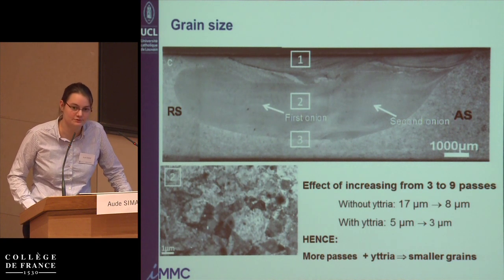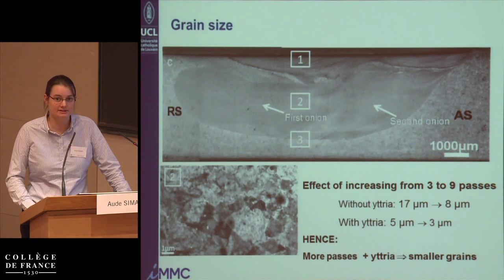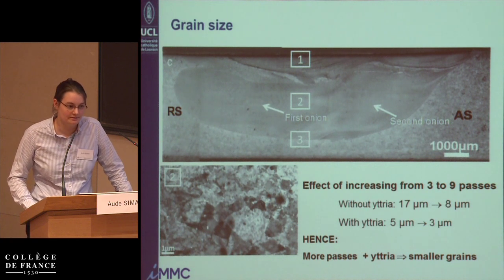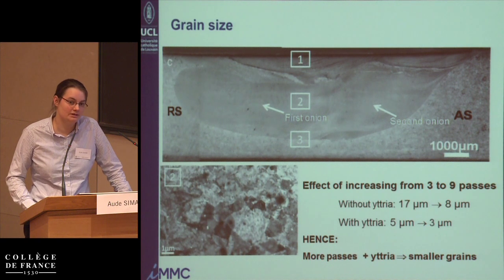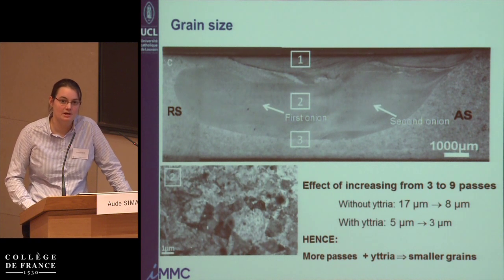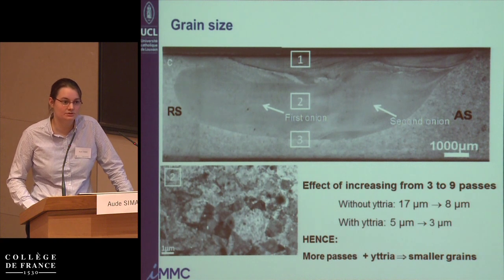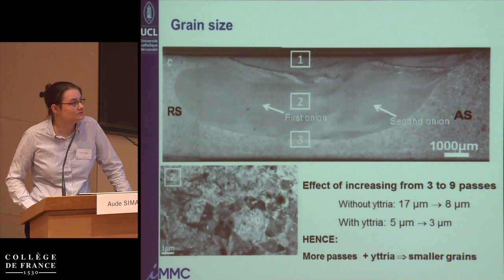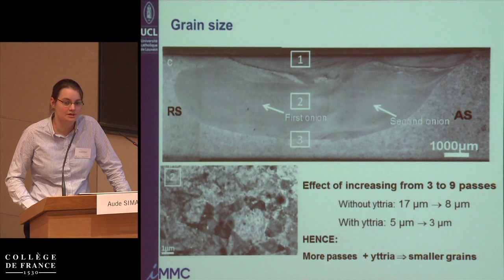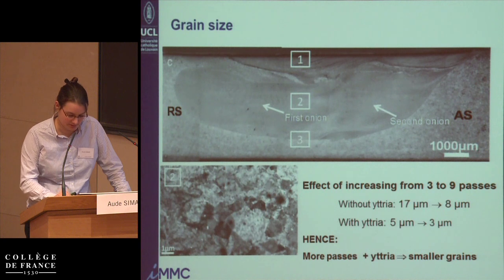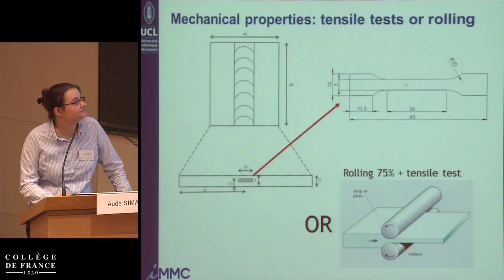And so that also improves the mechanical properties of the material, independently of the fact that you have nano-sized particles that will block the movement of dislocations, and so increase the strength of your material. It is also interesting to see that the grain size is decreased by the pinning effect on the grain boundaries, and that will also lead to smaller grains and hence potentially higher properties.